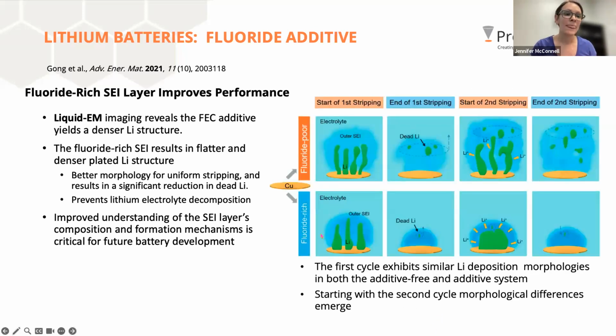But you can see their curves here, and upon more inspection, they summarize it with this cartoon. By adding fluorine into the SEI layer and creating a fluoride-rich SEI, they noticed that during the first charge-discharge cycle, with and without the additive, the dendrite growth looks similar and the redissolution is very similar. But once you get into the second cycle, the morphology looks quite different. Without the additive, you end up with the more classic trees or branches. With the additive, you get those globular ones again, which we learned from the last paper tend to redissolve better and more efficiently.